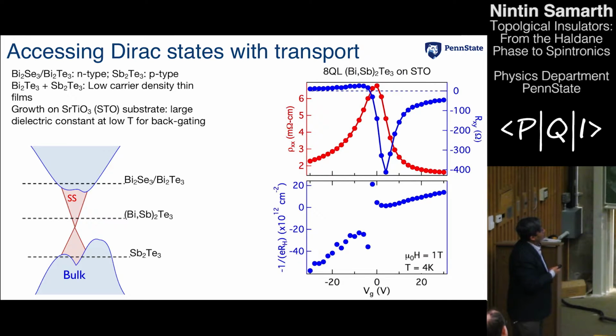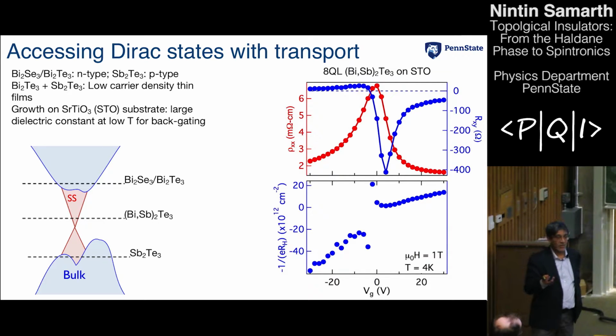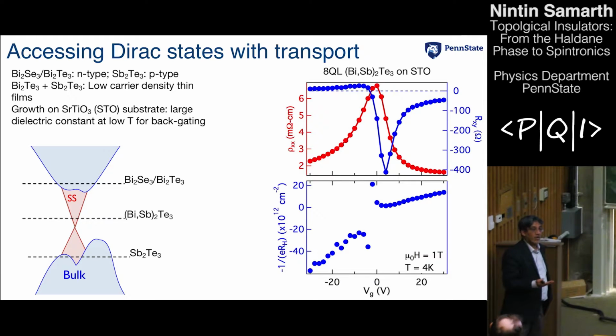Now, if on top of this, you grow the sample on a particular kind of substrate, something with a large dielectric constant, then you can effectively make a capacitor by putting a metallic contact on the back of the substrate. So you make a capacitor in which you can change the carrier density, or you can change the charge on your plates. And so this is called gating.